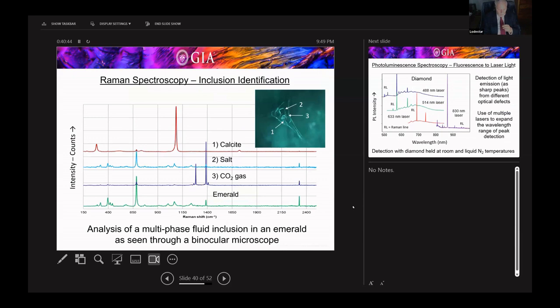But because you have a gemological microscope, what's very important is you can focus a laser on micro features. In this case, this is a multi-phase fluid inclusion in an emerald. And you can capture the spectrum of solid calcite, solid salt, a gas bubble, and the emerald by just analyzing different spots with this laser because it's aligned with the optics and the crosshairs of the microscope.